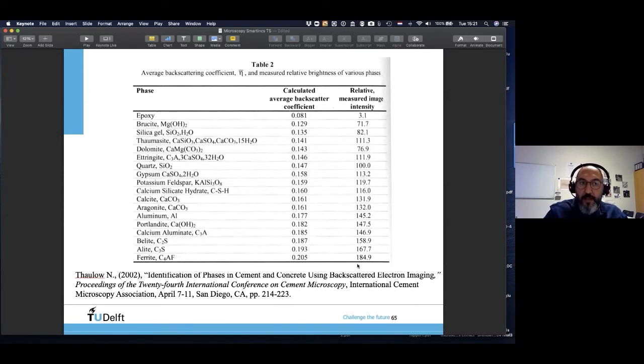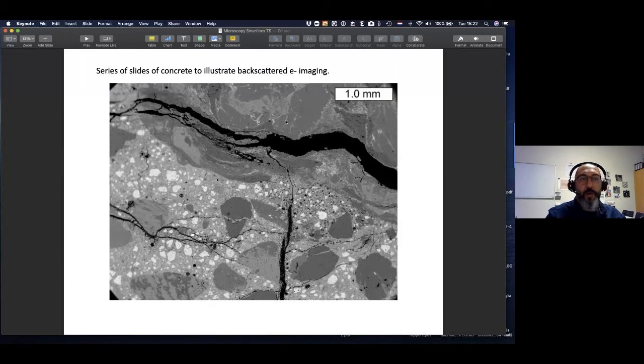You see, this is the darkest and this is the brightest. So if you're looking at an image of a cement paste, then you will see, for instance, ferrite, alite, belite, calcium aluminate phases as relatively brighter compared to your epoxy or silica gel, right? They will be relatively darker because their backscatter coefficient is lower. Why? Because their mean atomic number is lower, relatively speaking. So let's look at how we're observing our cement paste. This is a typical concrete microstructure. It's at very low magnification. So look at the advantage of backscattered imaging. We have filled in our cracks with epoxy.